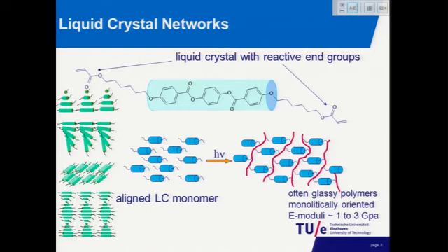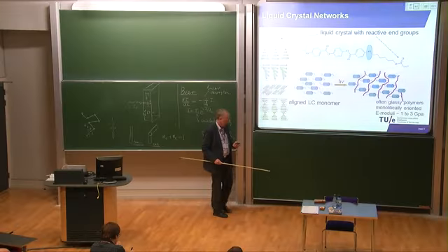Of course, orientation is then determined by the boundary conditions, and we can play with the boundary conditions, such, for instance, that the molecules are not uniaxially aligned, but make a twist over the thickness of the film. Or you can bring them into a bend or splay state, so it goes from planar gradually to a perpendicular state, which is called homeotropic state in the liquid crystal field. You can bring them into a tilt if you like, and you can add chirality into the molecules such that they start to rotate, and then the concentration of the chiral components determines the pitch of this rotation.